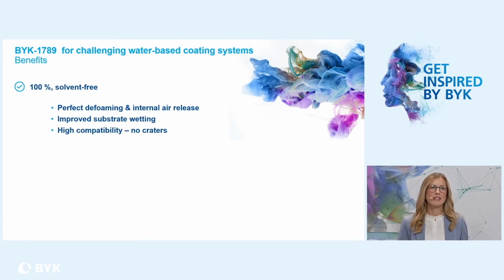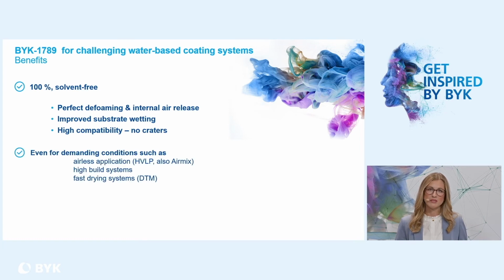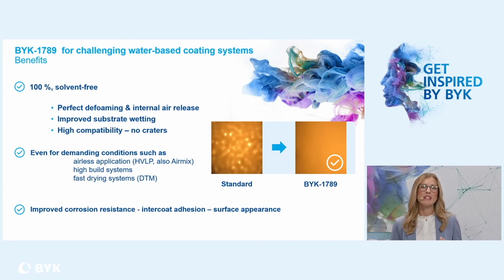So this is where I would like to introduce to you BYK-1789 as a perfect balancer which solves our challenges in water-based protective coatings. BYK-1789 is a 100% silicone-based defoamer with an excellent balance between defoaming properties on the one hand and a high compatibility in the system on the other hand. So this is really the defoamer which is used to get rid of foam in water-based primers, midcoats, and direct-to-metal coatings. And therefore, we really need this defoamer to improve the corrosion resistance in protective coatings.